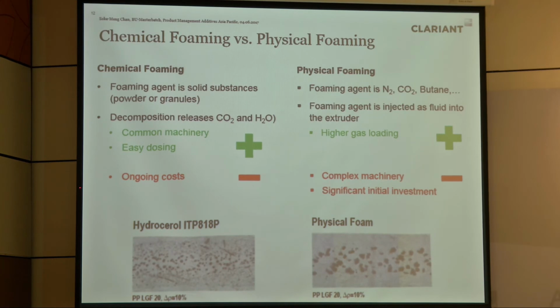Both left and right of the picture are based on PP long glass, 20% long glass fiber filled polypropylene. The delta P is the same, 10%. However, when you look at the cross section of the article, the one based on chemical foaming has a more homogeneous and smaller foam cell size structure. As compared to the right-hand side, the foam cell size is coarser. It's not as homogeneous as chemical foaming.